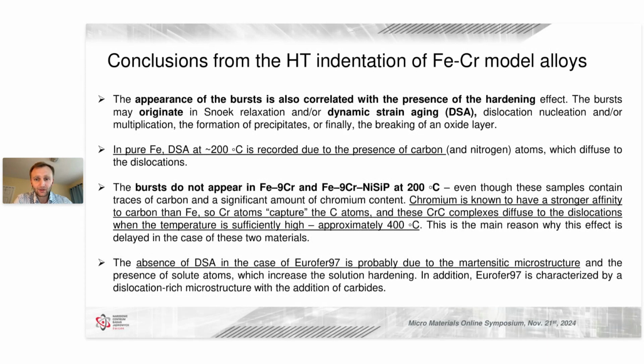This phenomenon is not occurring for iron 9% chromium and the same material with addition of solute atoms at 200, because we have chromium in the system. Chromium is known to have a much stronger affinity to carbon than iron, and basically creates complexes composed of chromium and carbon.